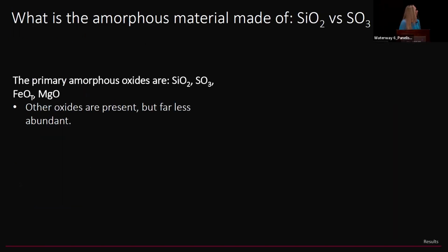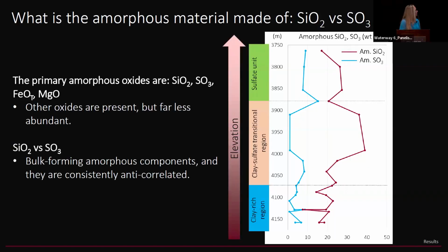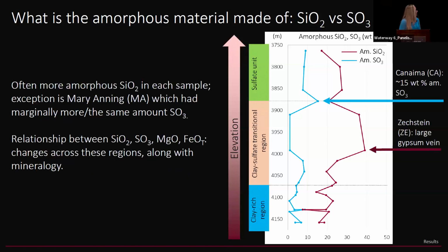So the next thing I want to talk about, and I'm going to breeze through this and it's really simplified, is what is it made out of? The amorphous component is primarily made out of SiO2, SO3, iron, and magnesium. There are other oxides, anything that APXS measures we can also get in the amorphous component, but they are far less abundant or the errors are often really difficult to work with. The first thing I want to point out is that the bulk forming amorphous material components are SiO2 and SO3, and they are anti-correlated. They are consistently anti-correlated across all of these regions.